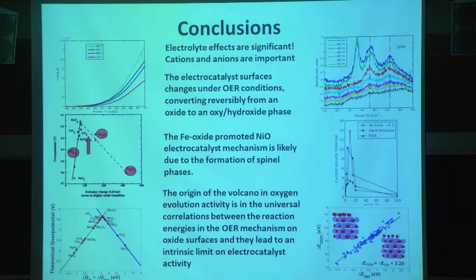All right, so I'm going to wrap up and conclude. So electrolyte effects are significant, right? You can double an apparent reaction rate, or in some cases, get an order of magnitude change in reaction rate just by changing the electrolyte. The electrocatalyst surfaces change under oxygen evolution conditions. This change is reversible as you go up and down. These peaks form and disappear.